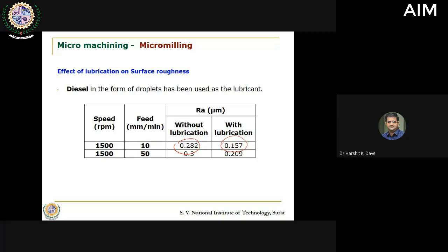to half, 0.15 microns. Similarly, for the higher feed, we got a roughness of 0.3 microns, which is almost similar to what we get. But here at higher feed, we got a roughness of 0.2. So there is probably a reduction of 1/3 of the roughness value. So that is one good observation that we saw.